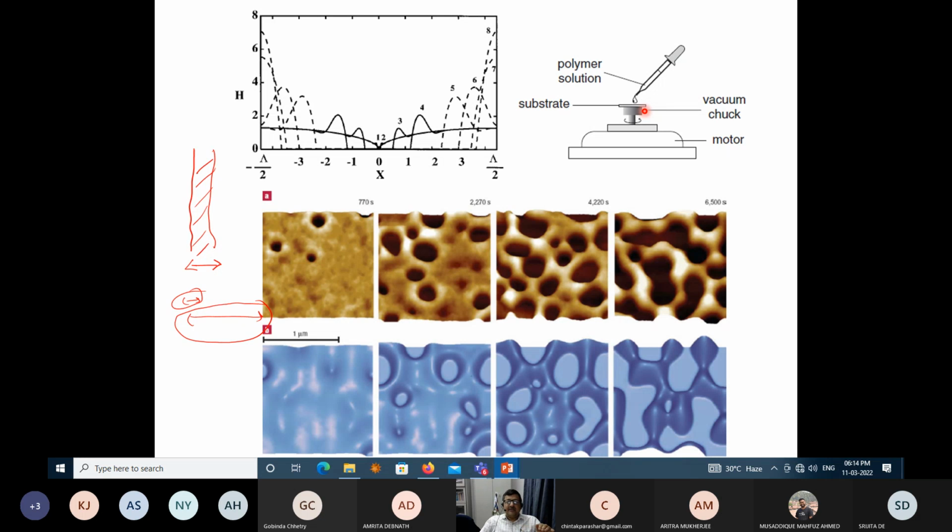It's in a fluidic domain. So you will find that a coating which is of very thin film thickness is going to disintegrate by forming some holes, and these holes grow, because the moment the hole is formed, you will find, like this is the 2D simulation, when the hole is formed, this is not under equilibrium contact angle, so you can see the hole grows, and as the hole grows, there is a reformation that is taking place, right? And then as the hole grows to achieve the equilibrium contact angle, they form droplets.